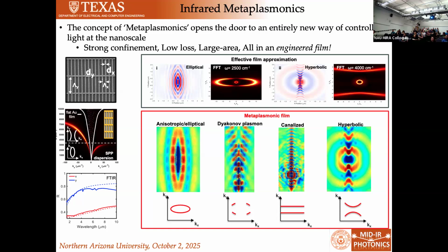And the mode, you can see it's highly directional, and the wavefronts have this sort of hyperbolic shape. When you transform that, this is just the dipole signal, but what you see is actually hyperbolic dispersion, right? And that can give you a massive optical density of states, all sorts of interesting things. In fact, I think the physics is even richer than that. You can go from anisotropic behavior to these things called Dyakonov plasmons. You can even get this crazy canalization effect, where your hyperbolic dispersion flattens out and you get single directional propagation, from anisotropic to hyperbolic behavior, all in the same film as you go through the different regimes of operation of this film.